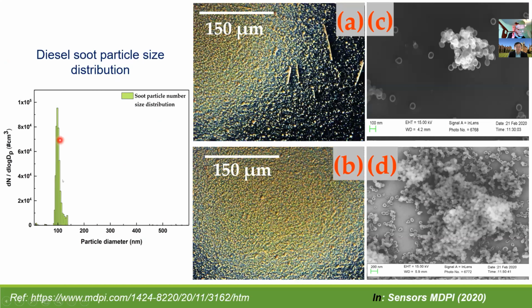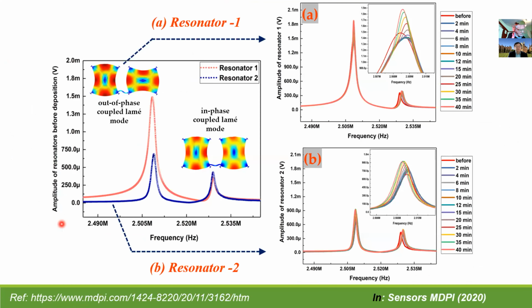So this is the size distribution of the 100 nanometer sized particles measured using the differential mobility analyzer, which is the reference instrument. And this graph shows the frequency and amplitude shift of the coupled resonators in response to the soot particles deposited for about 40 minutes on the resonators.